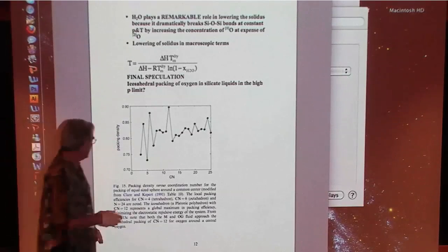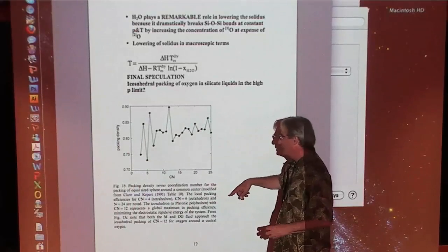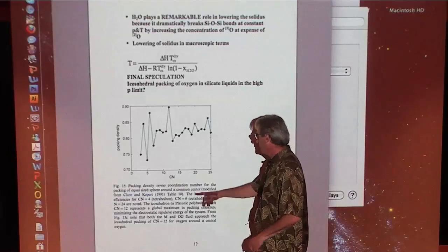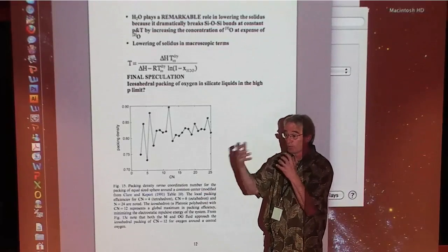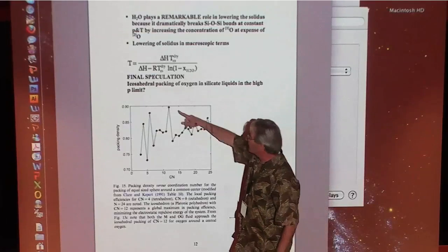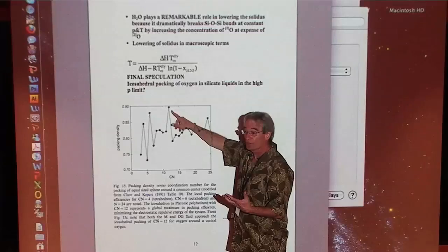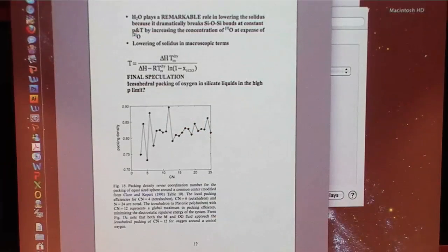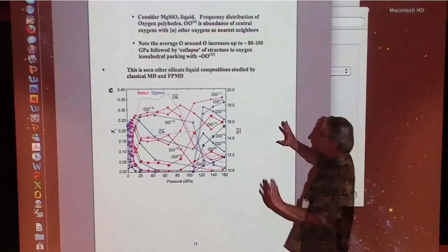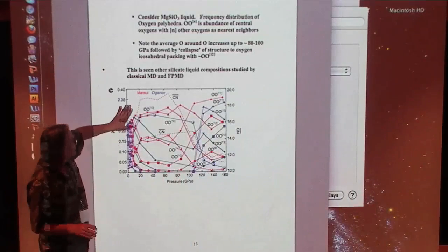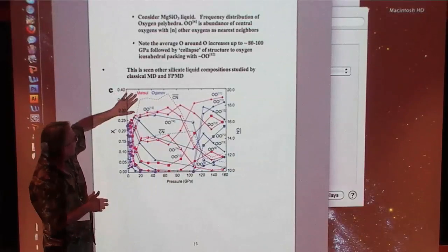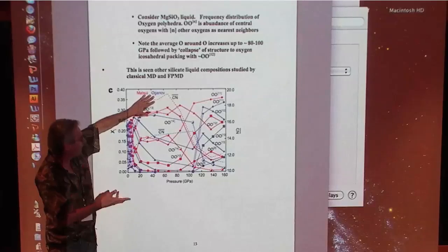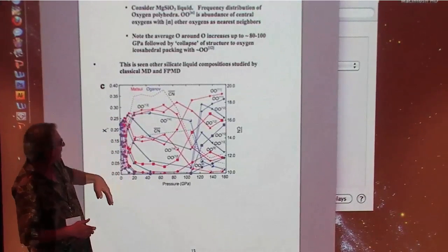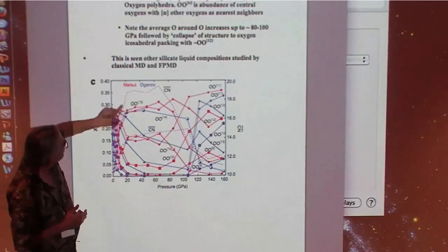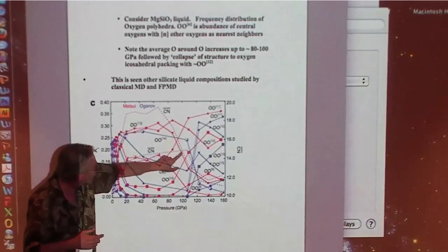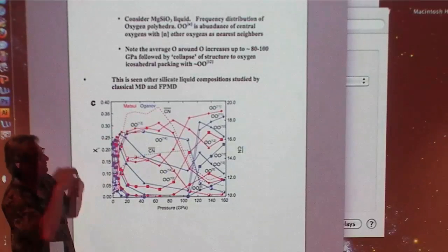And what this shows is the packing density versus coordination number for packing of equal size oxygen spheres around a common center where there are intrinsic repulsive forces. Oxygen's -2, right? And it shows that this is a really efficient way to pack oxygen, 12-fold. And if you look at this, and don't worry about this, this is MgSiO3 liquid. It's one empirical potential that we ran, and another empirical potential by Oganov that we ran. It's in the paper. But notice this dashed blue line is the average coordination number of oxygen around oxygen.